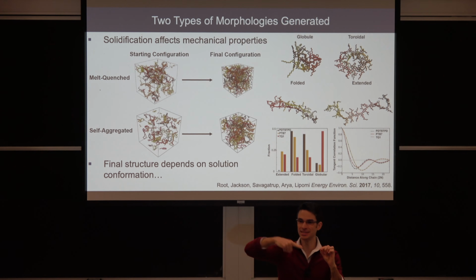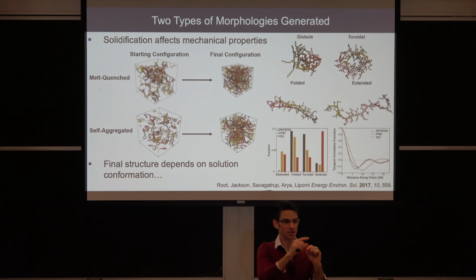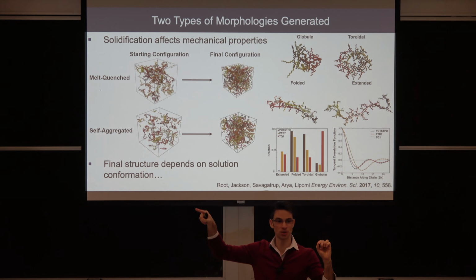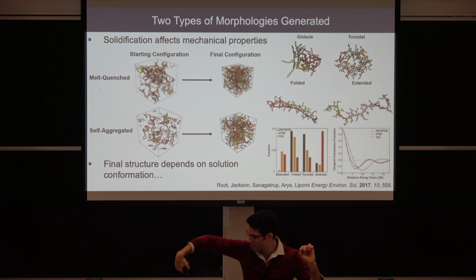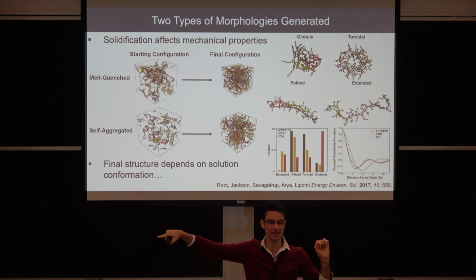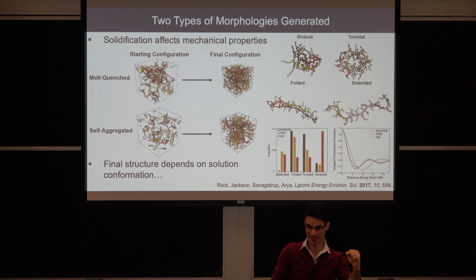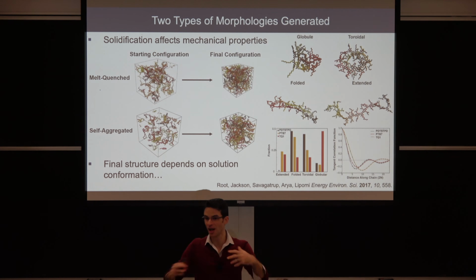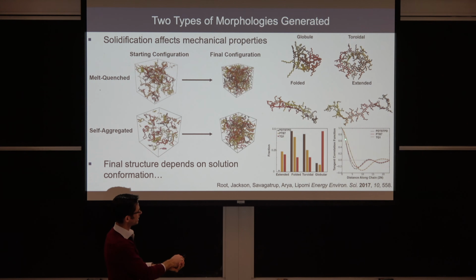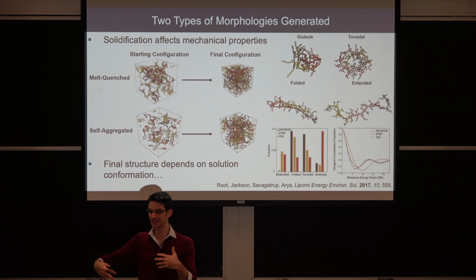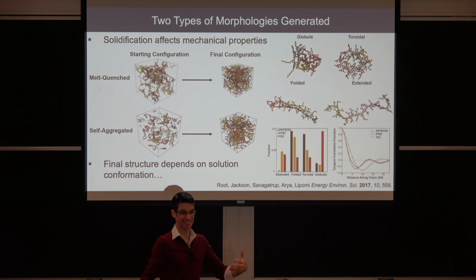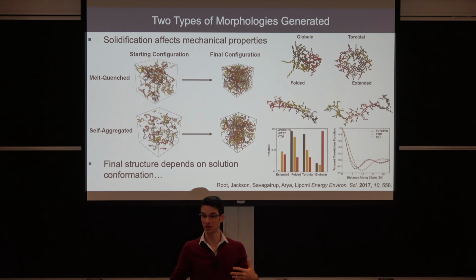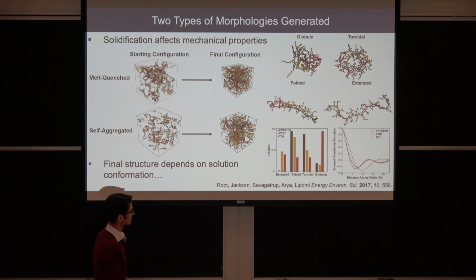But imagine if you had some helicity to the material, where you count down some number of monomer residues and there's correlation, because now you can predict with some amount of accuracy the probability that you'll be pointed in the same direction as the first tangent unit vector. So in the case of a globular system, we expect an exponentially decaying tangent correlation function as you go along the chain. But we don't have that here. We have this oscillatory behavior, and the oscillations are the result of these helical or ribbon-like twists or ribbon-like bends in the chain, which is not something that had been explored before.